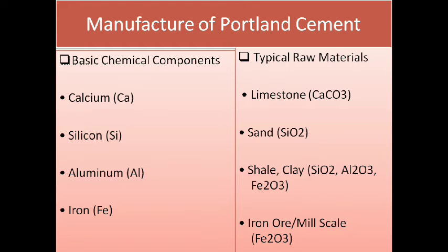Here SiO2 is 23% of the composition in an Indian Portland cement. Then Fe2O3 is about 2.19%, then Al2O3 about 5.97%, then calcium oxide, from calcium carbonate, 64.86%, then magnesium oxide 1% and SO3 1.75%, which are minor requirements.